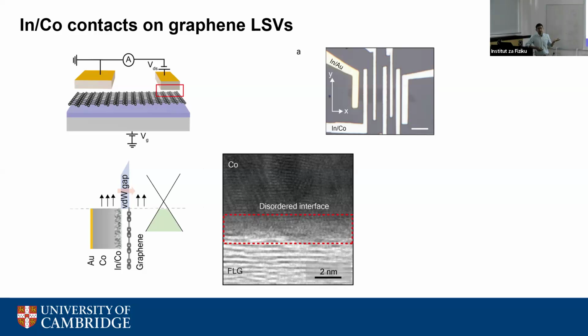And we have not seen any predominant effects of these residues on the growth, because we think that the residues are really not what is causing the damage. It is the evaporation of the metals and the kinetic energy of these metals which is causing the defects.